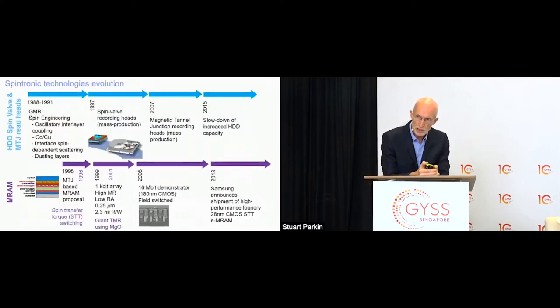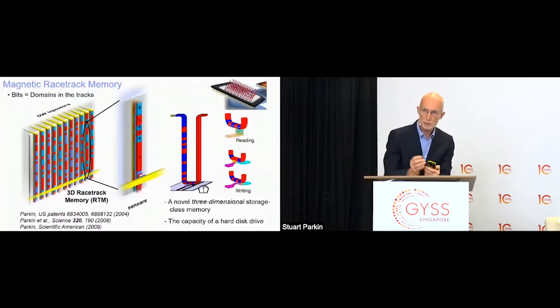But you can also see in the cartoon, what we do is we move the information which is encoded in the domain walls between the blue and red region. We move that information around the racetrack by passing current pulses into the racetrack. And these current pulses, if they're spin polarized, will develop spin torques onto the domain walls, which can move them. And my proposal was all the domain walls should move at the same speed together synchronously.